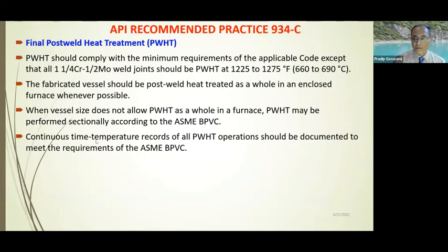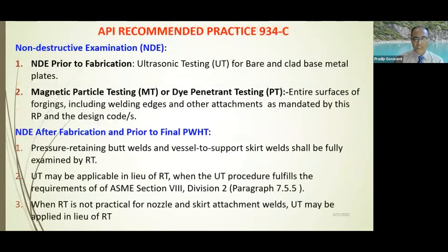And during any post-weld heat treatment, continuous time-temperature recording and monitoring definitely is a requirement, and that has to be monitored and documented. And NDE, or non-destructive examination, prior to fabrication, should be UT for the base metal and the clad base plates. PT for the entire surface of the forging, including the weld edge and other attachments, as mandated by this RP and the design codes, that is Section 8 Div 1 or Div 2.